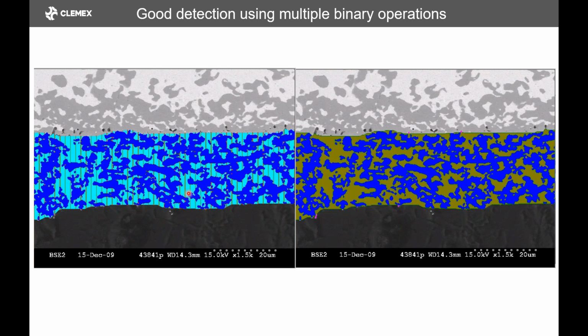So in this case, we're using a gray operation to delimit the lower line, and so we end up with the proper detection, and then we can do an area percent of the blue versus the light blue. The light blue, we can see here, is kind of greenish. That means that all the colors are merged. So when we measure the blue versus the background, the blue is included in the whole coating itself. And then we measure an area percent of the blue versus the light blue.